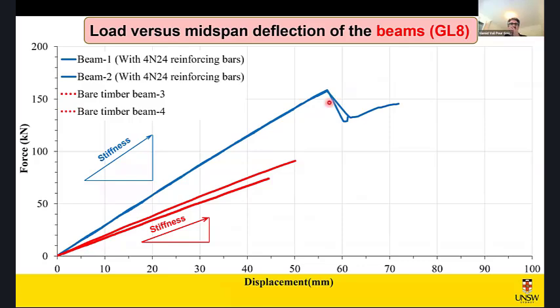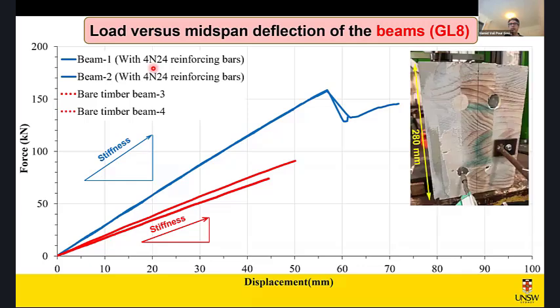Now let's look at the other beam, which is a GL8, and this GL8 was tested with two types of reinforcement. I just showed you the results of reinforced beam with N-class bars. So the yield strength is 500, and it's normal ductility reinforcing bars. So this is the beam you see on the right, 280 millimeter deep, and it consisted of 3 lamellas, 195 millimeter wide. These are the location of the bar. We use 4N24 bars.